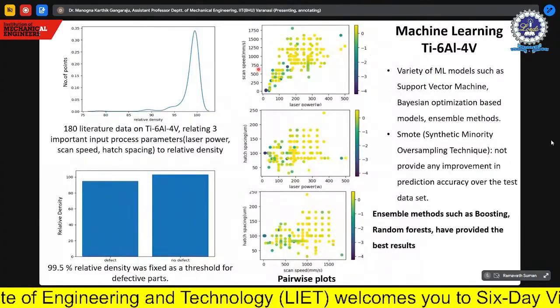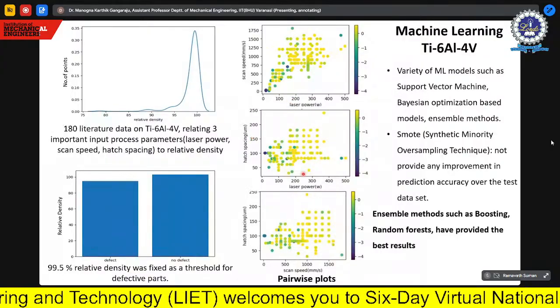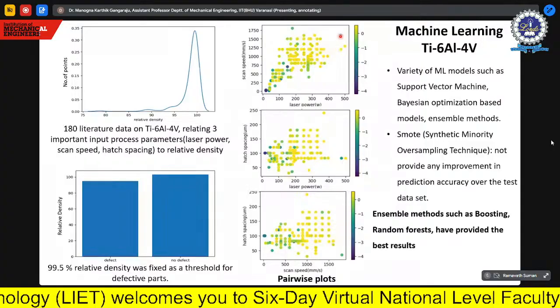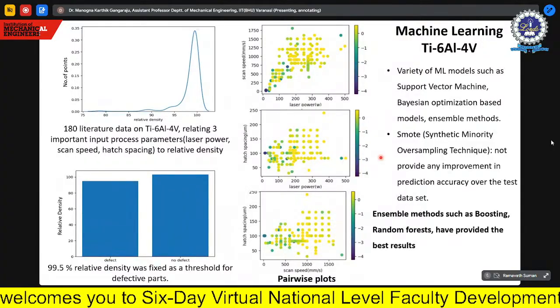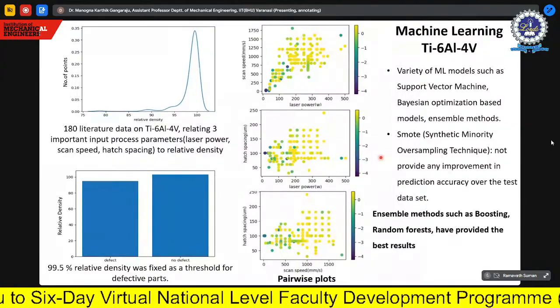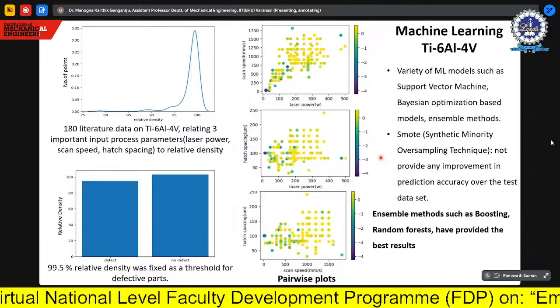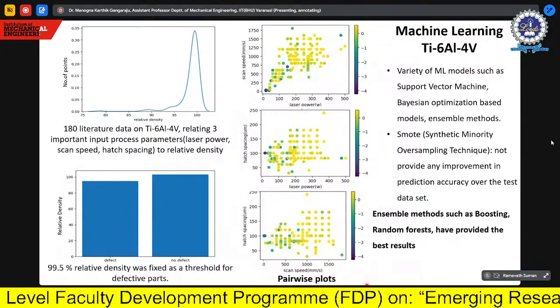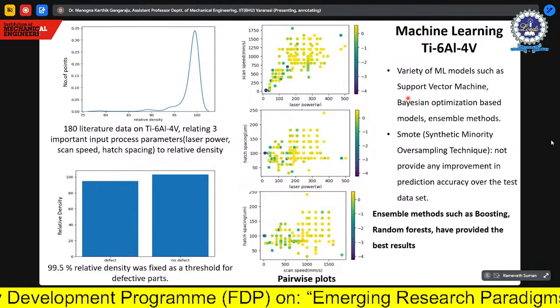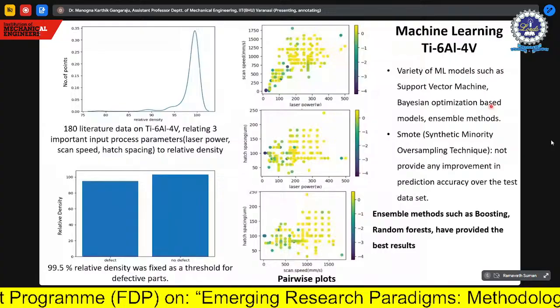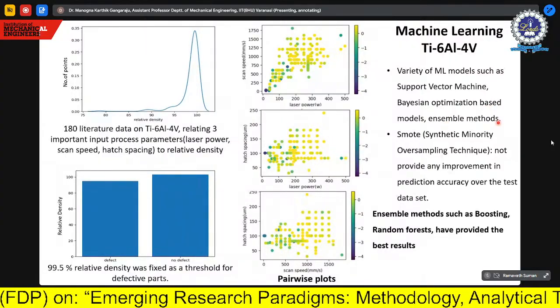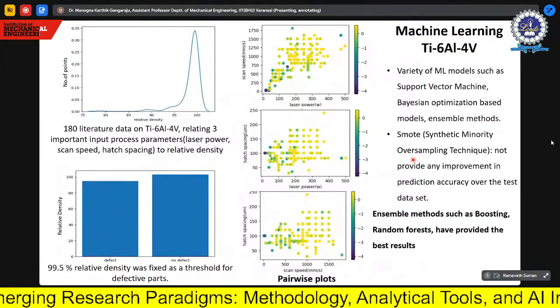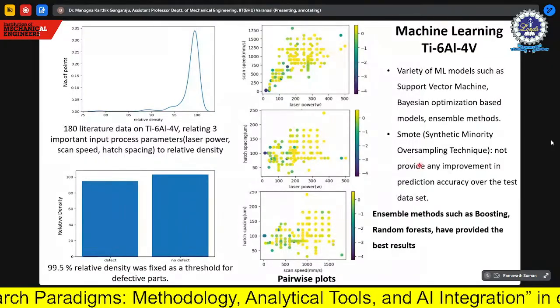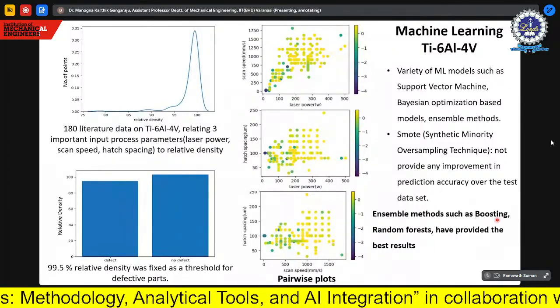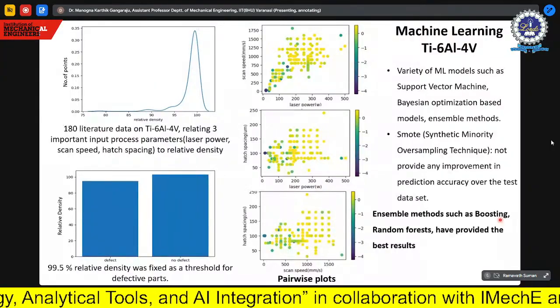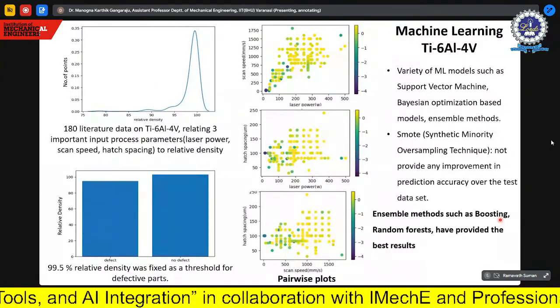So we found a correlation between scan speed, laser power, and hatch spacing. These are your pairwise plots which will give you the relationship between them. And we see that there is a fairly good relationship between the scan speed and laser power. Whenever you have these, relationships are important. Then we applied different ML models like support vector machine, Bayesian optimization based model, ensembling methods. Okay, and we also looked at synthetic minority oversampling techniques. But most of these methods did not give us good predictions. Only ensembling methods, boosting and random forest methods actually provided us the best result.